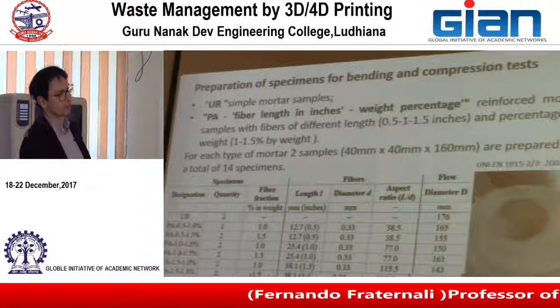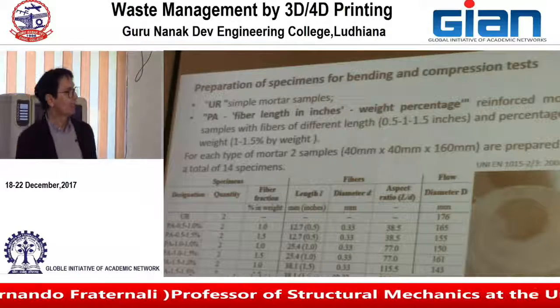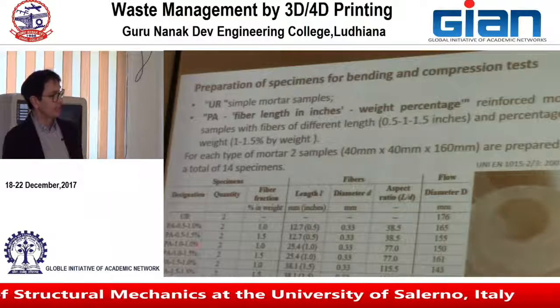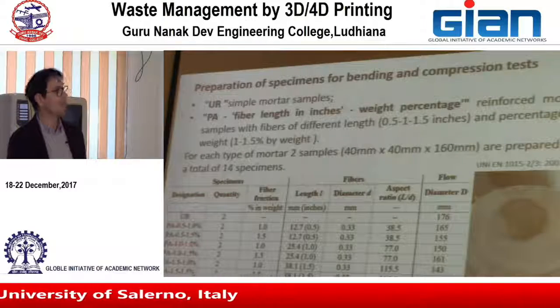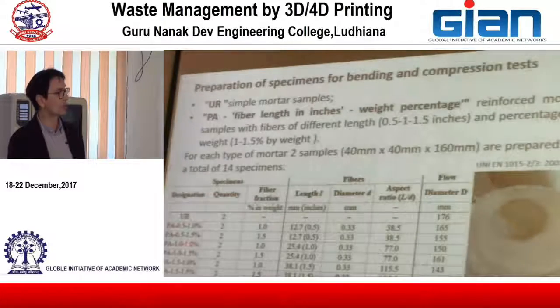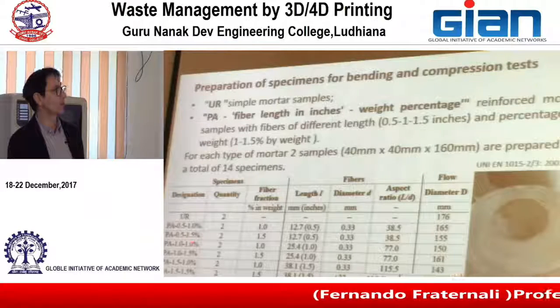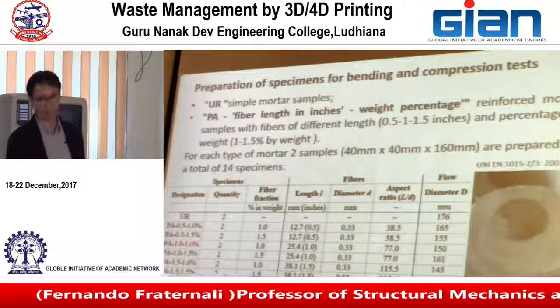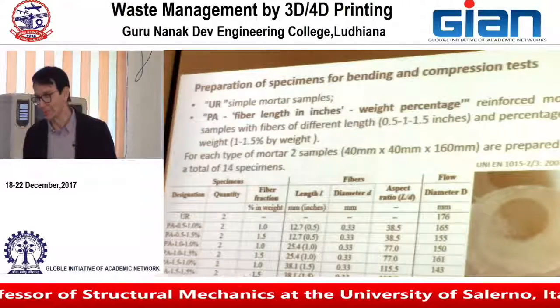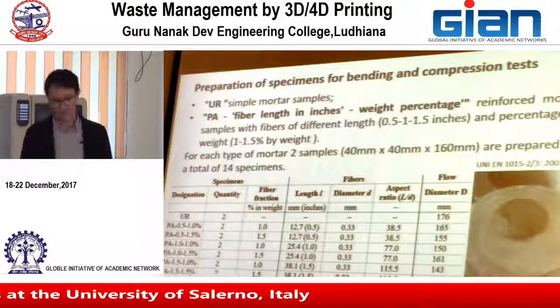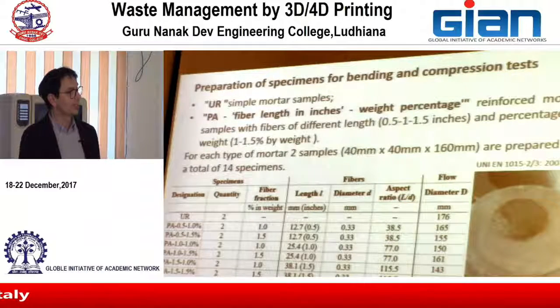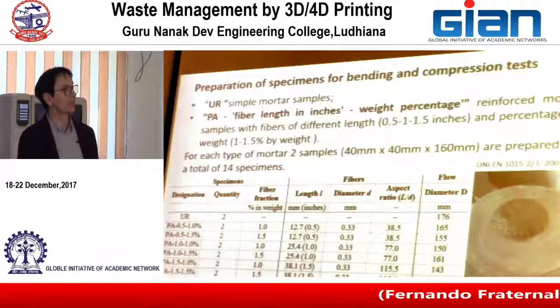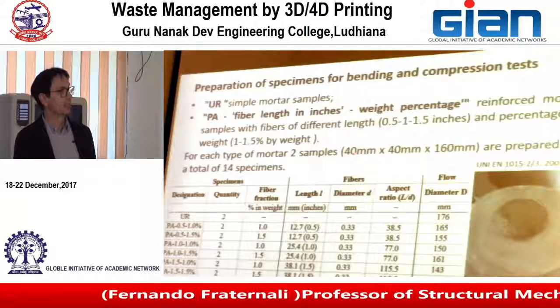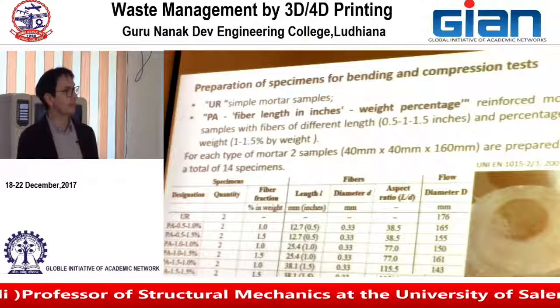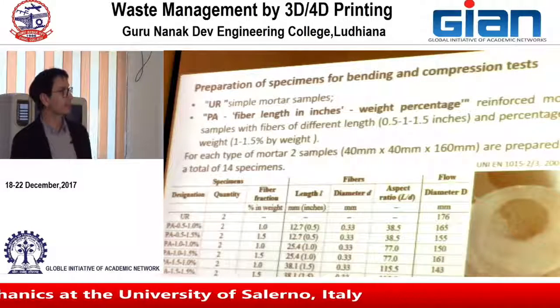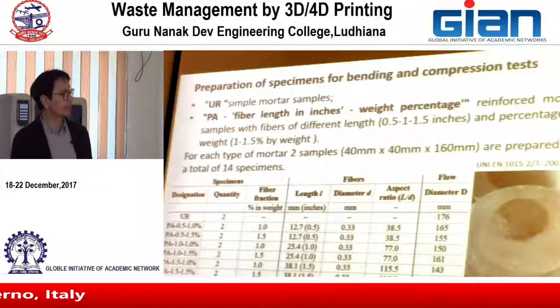Then we mixed the fibers to a commercial mortar, and in this case, we considered 1% fiber weight content or 1.5% fiber weight content. The mortar specimens are different from the concrete specimens. They are different scale. So in these cases, we tested prismatic specimens with 40 by 40 by 160 millimeters sides, and we tested two specimens for each different material.